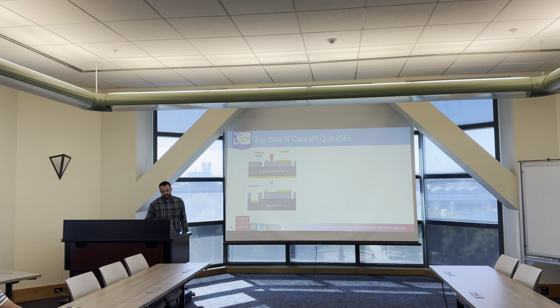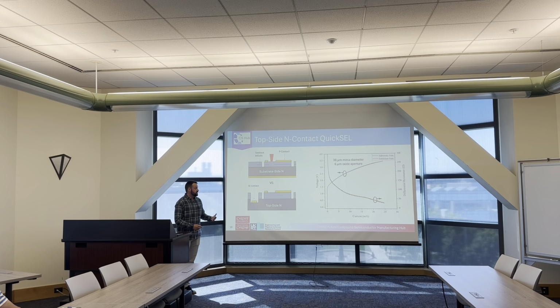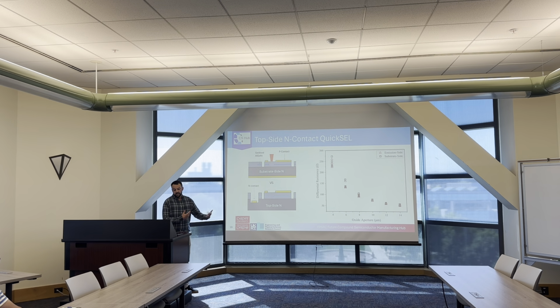Then we also qualified the top side n-contact need for structures that are grown on semi-insulating substrates, looking at the effect on the resistance of the device. It's pretty much equivalent, and then again, more obvious when you look at it as a function of device size, and for a larger amount of devices, there's no effect on the resistance by depositing on the backside or the top. Okay, so that was an overview of QuickSELs.